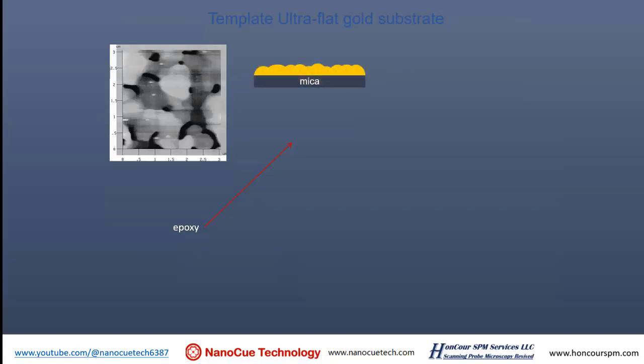So you have mica, and you evaporate gold on the surface. The yellow stuff represents gold. And you can glue a piece of glass or silicon on it using epoxy. Just glue it. And then you don't just glue one piece, you glue a lot of pieces. So every time you evaporate a piece of mica, it's a large sheet of mica, and you glue a lot of little coins of silicon on it.